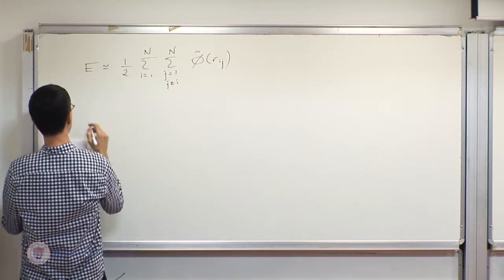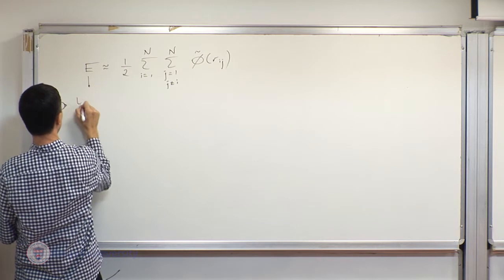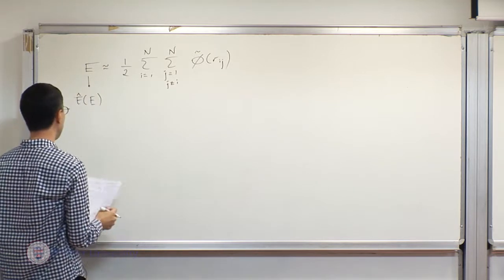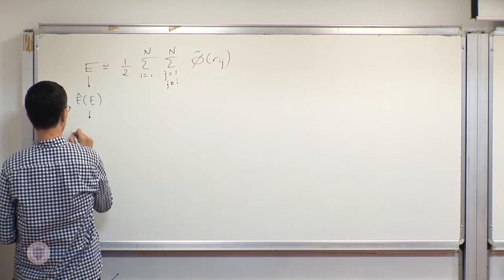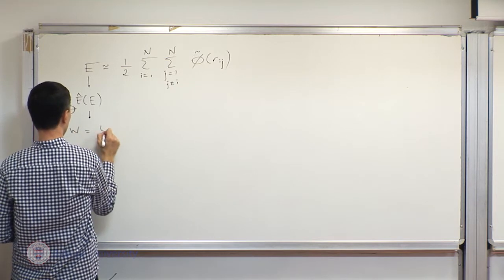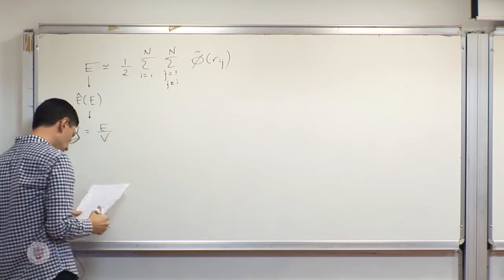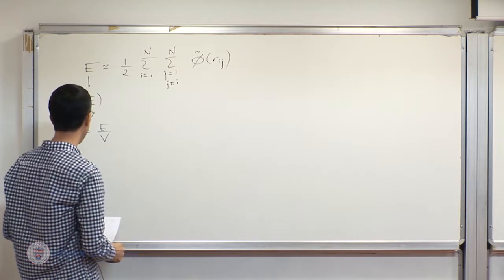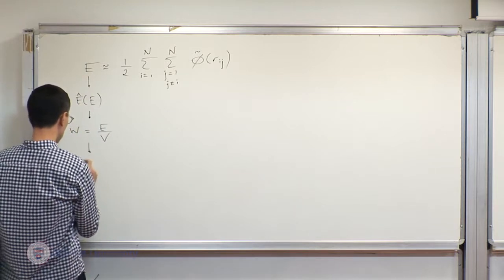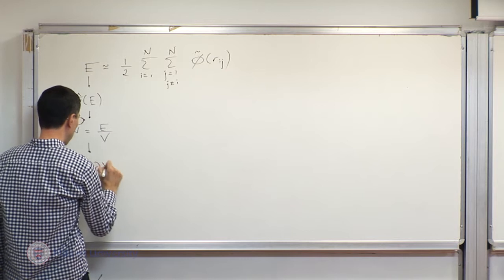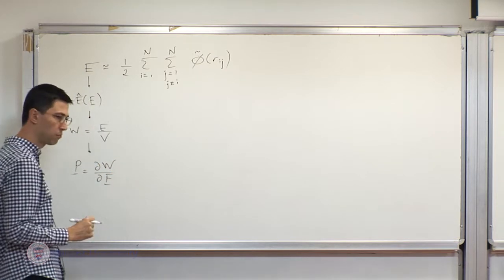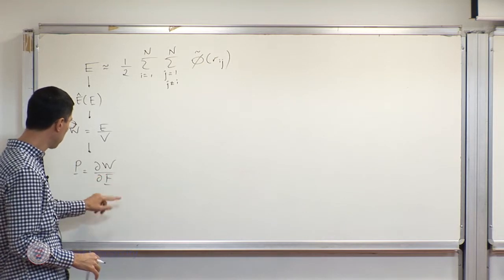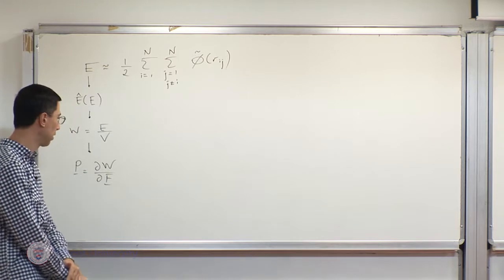From that assumption, we made a transition to the macroscopic strain energy function, which is E divided by the referential volume of the crystal portion being analyzed. Based on the concept of hyperelasticity, we deduced that we can calculate the stress that the crystal is subjected to if imposed a deformation characterized through F.